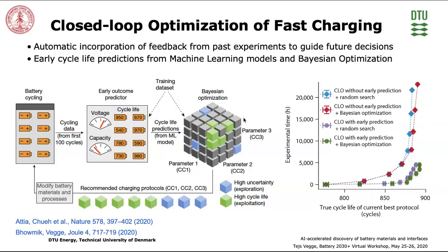This is work from Will Chueh's group at Stanford, where they actually take already existing materials and try to improve the performance of those. So by doing machine learning to establish early cycle life prediction, combining that with Bayesian optimization for optimizing fast charging procedures, they are actually able to improve the performance of existing materials by optimizing the way that the fast charging is performed. So as you can see out here, significant improvements.